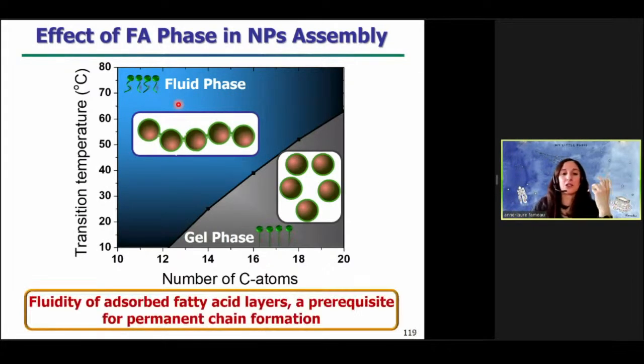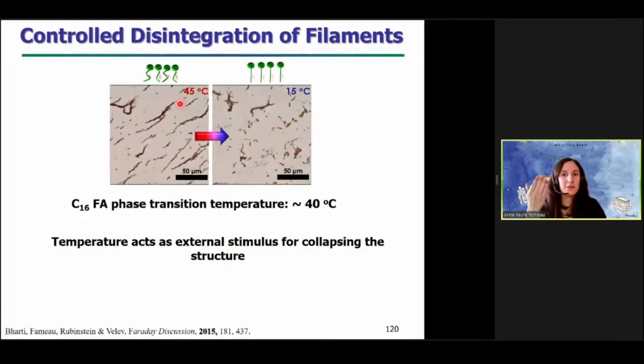So this clearly shows that the fluidity of the adsorbed fatty acid layer surrounding the particle is really the prerequisite for the permanent chain formation, because if you don't have a fluid layer, they can't form the capillary bridges that bind all the particles together. But we use the fact that you have this transition between gel phase and fluid phase to control the disintegration and the formation of these filaments.